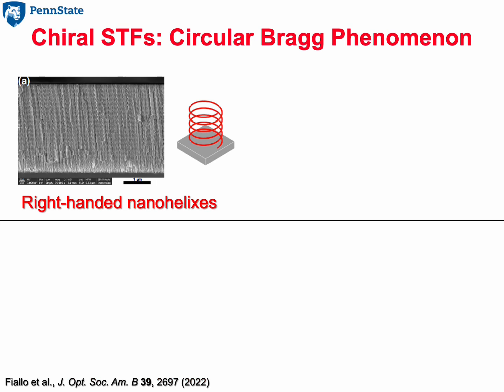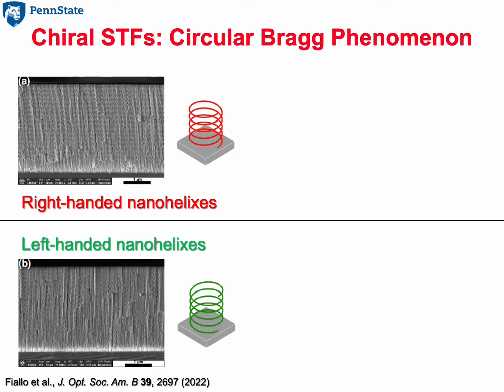Let me go on to chiral sculptured thin films, which are assemblies of nanohelixes. On the top, you see a structurally right-handed chiral STF. On the bottom is a structurally left-handed chiral sculptured thin film. Polarized light can also be chiral. Now suppose that circularly polarized light falls normally on a chiral sculptured thin film. If it has the same handedness as the chiral sculptured thin film, then this light will be highly reflected. If the two handednesses are opposite, then the reflectance will be small.